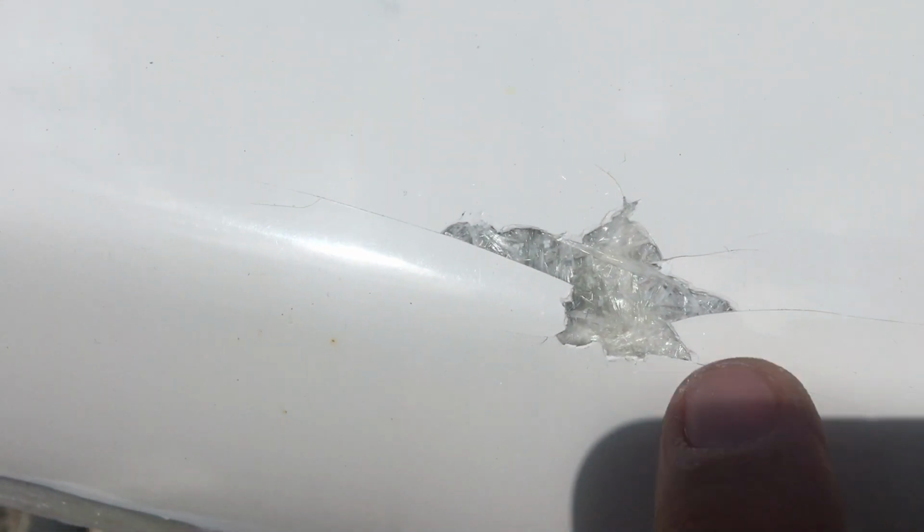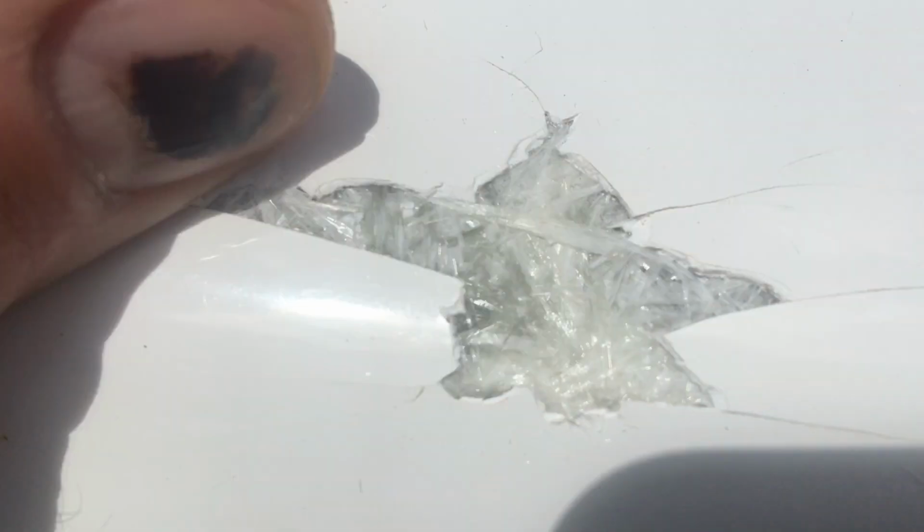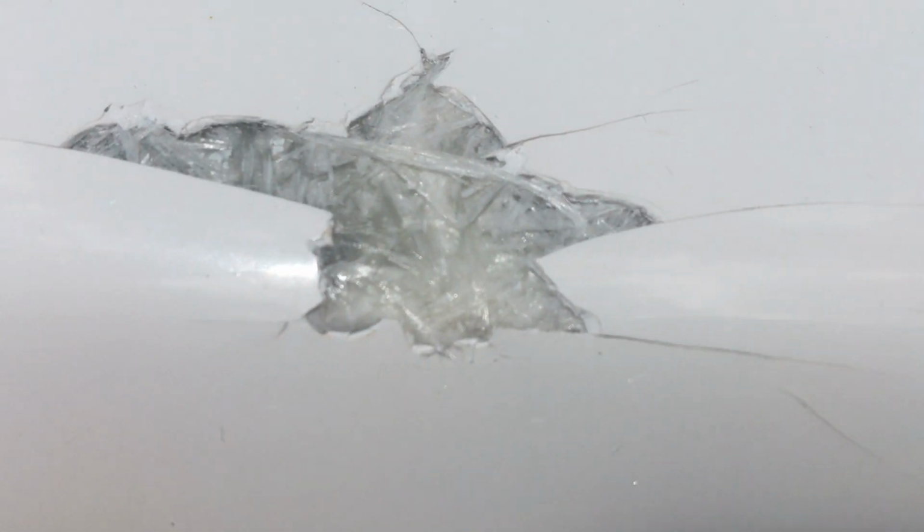The other thing that we found was, I don't know if you can see, the fibres are not actually resin, they're all dry. So see if I can get a better shot. Yep, and then you can see the crack stemming that way, and if you keep following down you can see there's actually one all the way down to another one here.